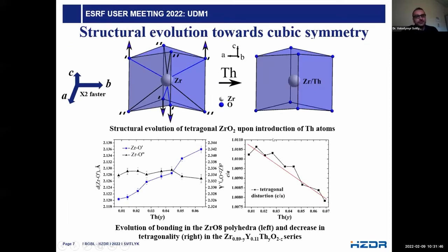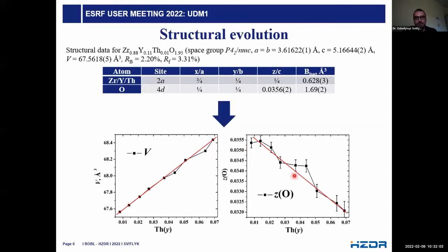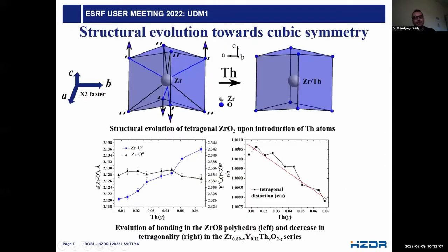So what it would imply from a structural point of view: in a tetragonal zirconia, there are two sets of oxygen atoms. I mark them here, oxygen prime and oxygen double prime. So you have two sets of distances. And if you have this kind of change in the oxygen z coordinate, by symmetry you expect that zirconium-oxygen prime distances would become longer, so these atoms would move farther away from the central zirconium atom, and the zirconium-oxygen double prime distances would decrease. But what we observe is that only these zirconium-oxygen prime distances increase, and it results in flattening of this zirconium polyhedra. So indeed, you see these blue distances increase, and these bonds, zirconium-oxygen double prime, are stabilized.